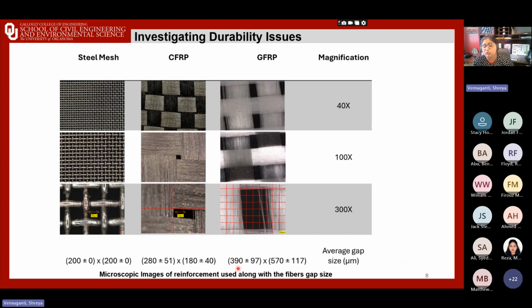Also, notice these details matter because the pore size and geometry affect bonding with cement paste and also the resistance to crack growth. So we wanted to use these 3 different reinforcement strategies as the variables and essentially study how they impact the durability of these interfaces and eventually in the 3D printing as well.